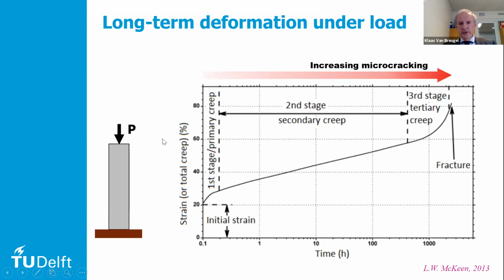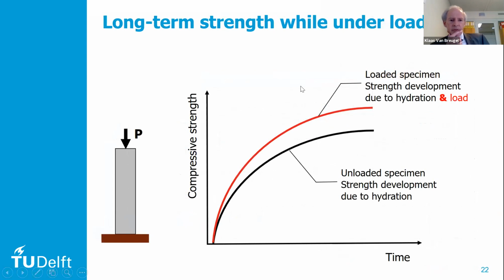But we see also something else. Here you see the increased microcracking indicated, but we can also look at the strength, not at the deformation, but at the strength. And then you see that the strength will gradually increase with time due to hydration. But if it hydrates under load, as indicated here on the left cartoon, then you see that in the end, the strength is higher. And that's interesting because in the previous picture, we saw that due to cracking, there was in the end the failure, progressive failure, sudden failure at the end.